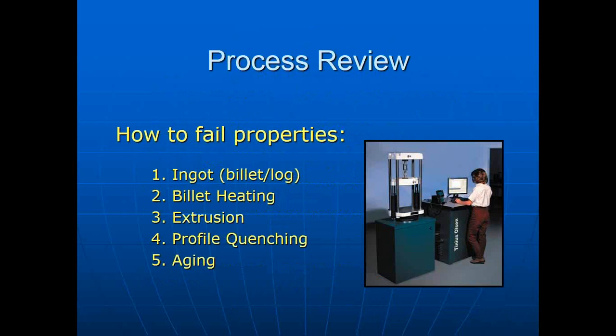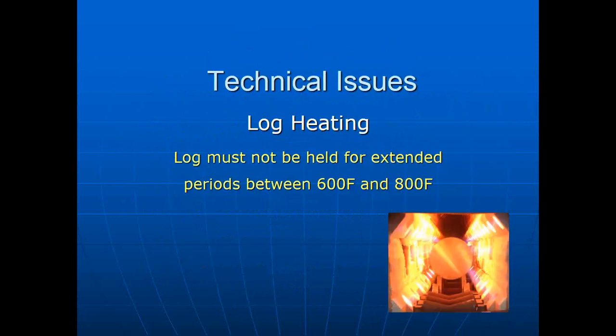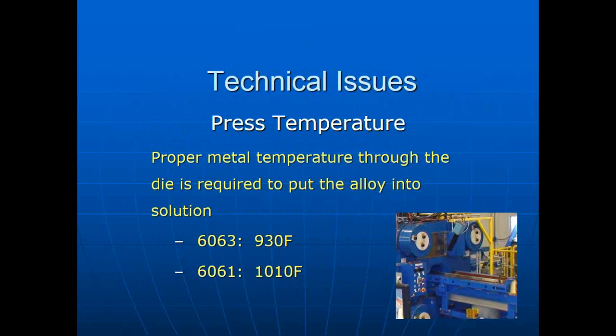The first is the processing of the ingot, billet or log. The structural alloys are very sensitive to precipitation, growth of mag silicide, again, we're going to get into that in a minute, between 600F and 800F. And if you have reason in your heating equipment to hold a log in that range for some period of time, you will develop large enough precipitates that you will not be able to resolutionize as you go through the press, and it will lead to product failures.